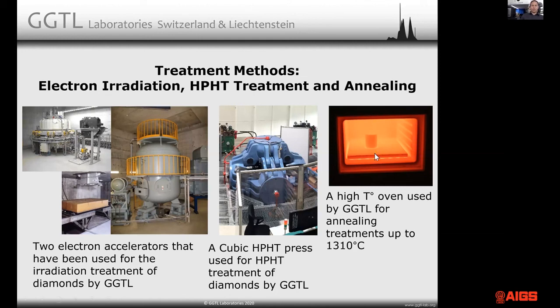Then heat treatment is used, consequent to electron radiation, to change the color further. We do this here at the laboratory directly. And then for HPHT treatment, you use this kind of press, like the one shown here in the middle. It's a cubic HPHT press, the same thing that you use for synthetic diamond growth, HPHT synthetic growth.